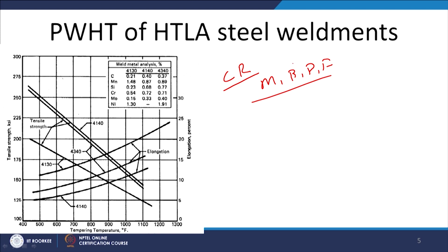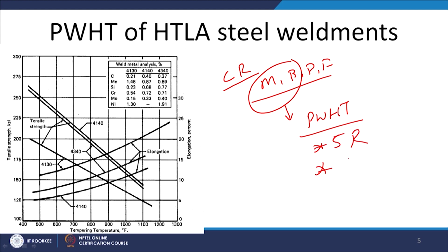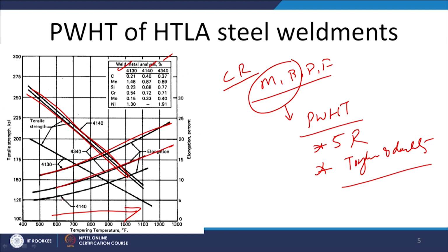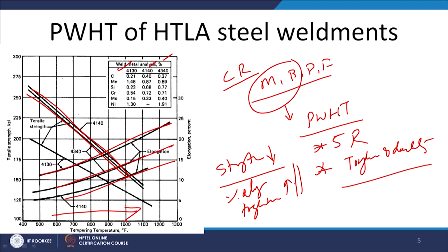So, especially if the weld joints are having martensite and bainite, then subsequent post weld heat treatment becomes important for two purposes. One is to relieve the residual stresses if these have been developed in the weld joint, and the second is to induce suitable value of toughness and ductility in the weld joint. So, in this post weld heat treatment, where tempering is performed on the weld joints, increase of the tempering temperature simply reduces the tensile strength of the different grades of the HTLA steels. On the other hand, there is a continuous improvement in the ductility. So, in general, with the increase of tempering temperature, strength decreases, and percentage elongation and the toughness in general improve with the increase of the tempering temperature.